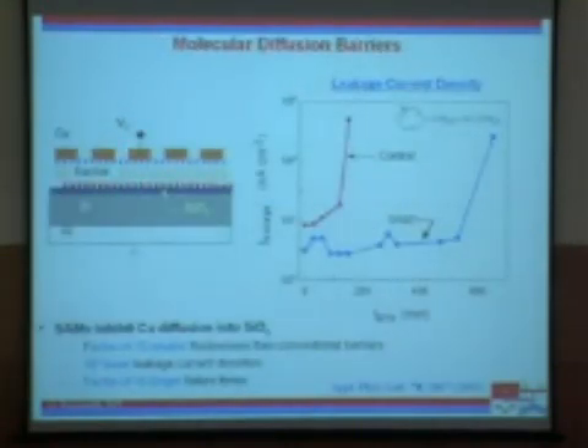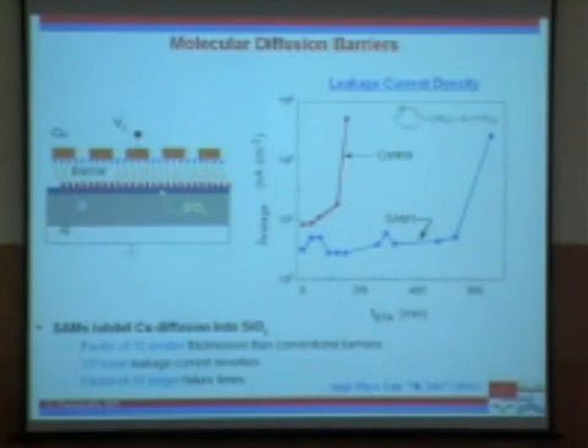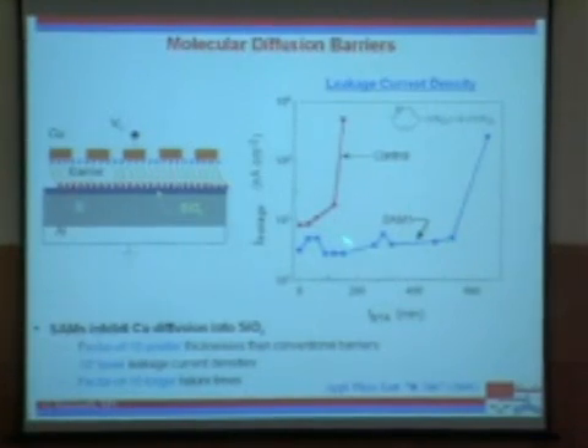So we actually make metal oxide semiconductor structures to study the diffusion, or the transport, of copper across. When we have no molecular layer in between, you can see that the leakage current goes up rather quickly, and this corresponds to the breakdown of the SiO2, and this happens at rather low times. But once I put a single molecular layer, and the thickness we are talking about is 1 nanometer, 2 nanometers max, you can see that the failure is postponed,